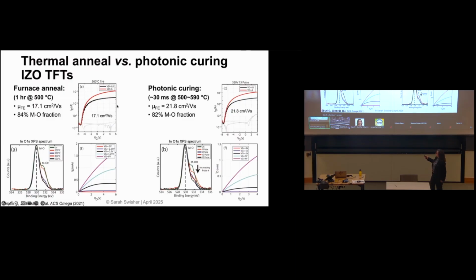And you can see, for those of you who are familiar with oxide semiconductors, this is my XPS showing the binding of the metal to the oxygen versus the metal to the hydroxide group. And you can see that as you heat up the substrate to higher temperatures, we know that hydroxide peak goes away. We see exactly the same thing happening here as we increase the number of pulses that we're giving to that film. And so increasing the pulse number gets rid of that hydroxide peak and gives me that high quality semiconductor that I want. And we end up with a mobility that's actually higher in our photonically cured transistors than in our thermally annealed devices.